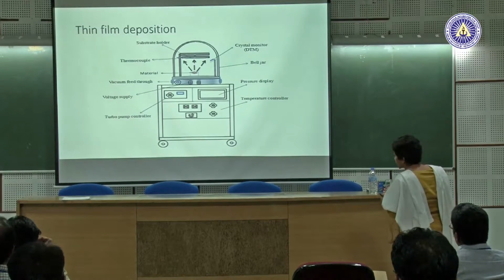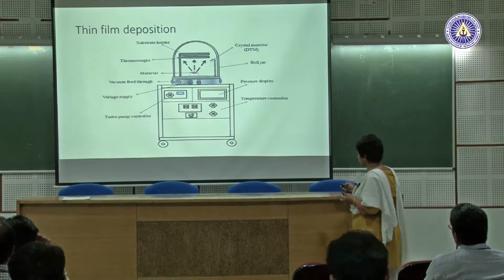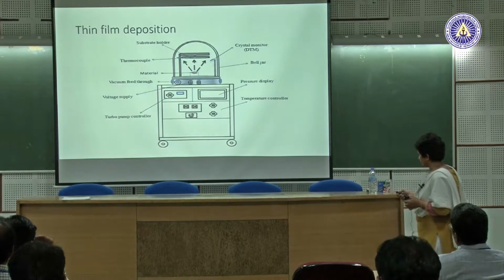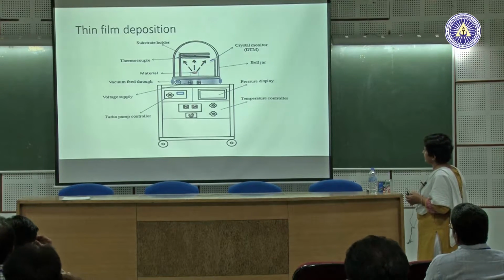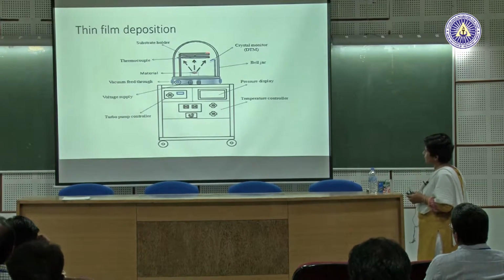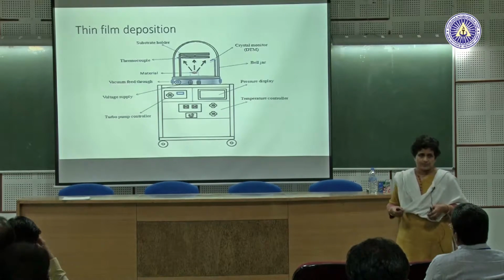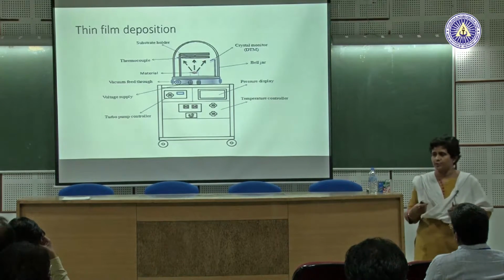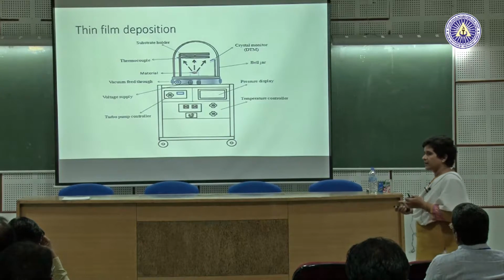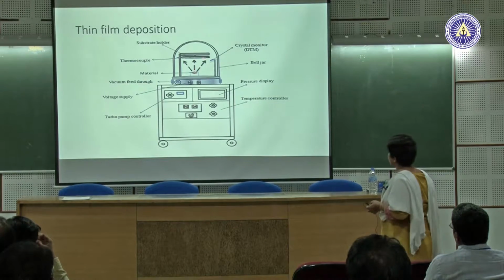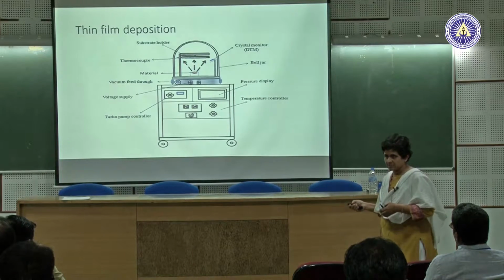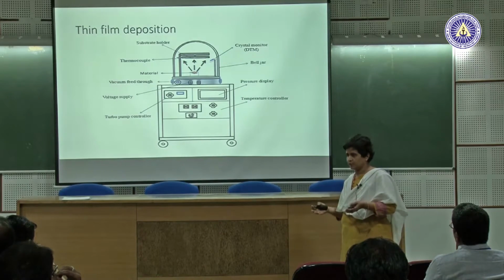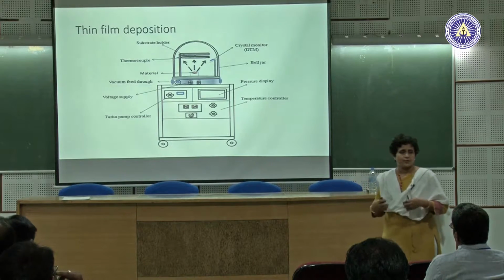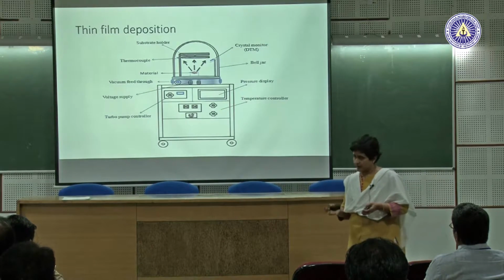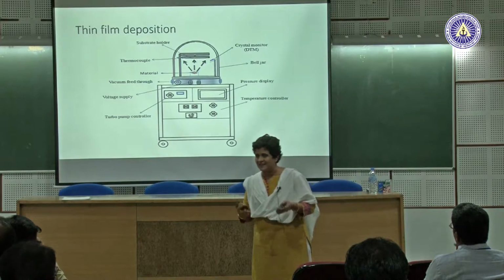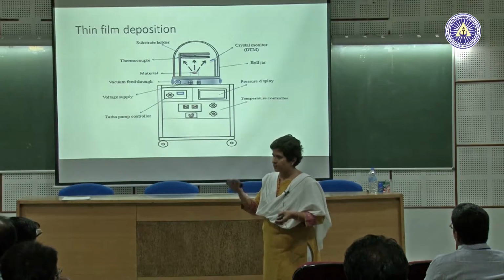A very simple typical thermal evaporator would basically have a chamber, and a very important part of it is that we do the evaporation in the vacuum. Okay. Now, there are many reasons for doing it in vacuum. One is you can create the partial pressure for deposition at a much lower temperature than if we were to do it in atmosphere. That is one reason. Second reason is if you heat up something at atmosphere and evaporate it in the form of atom, it will immediately react with the oxygen around it or the atmosphere around.